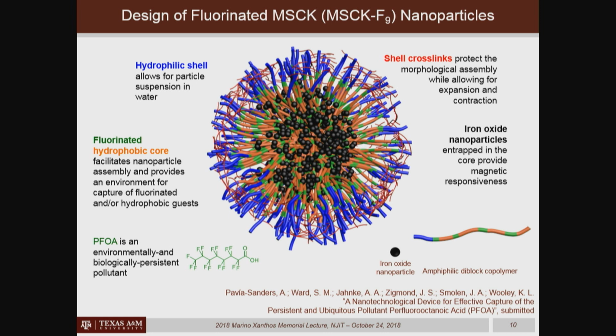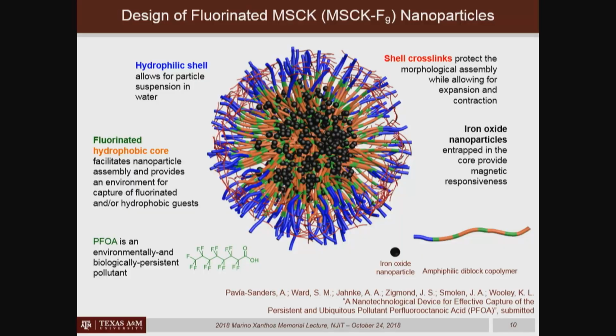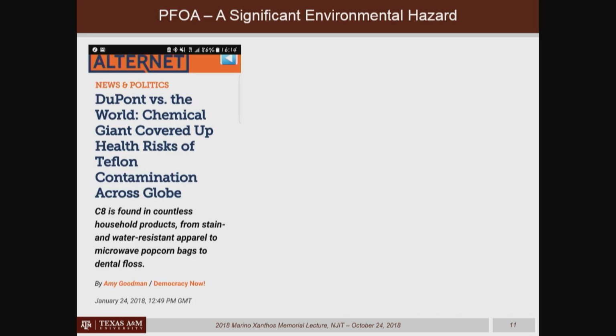So Adriana had said, well, let's take these magnetic shell cross-linked Knedel-like nanoparticles, and now instead of just having polystyrene, let's put some fluorocarbon into the core and see if we can pick up the perfluorooctanoic acid through a combination of fluorophobic and hydrophobic effects in the core domain. And she also then wanted to tune the chemistry of the shell to not only be polyacrylic acid, but maybe look into putting some amino groups in the shell that could interact electrostatically with the carboxylic acid head group of the perfluorooctanoic acid.